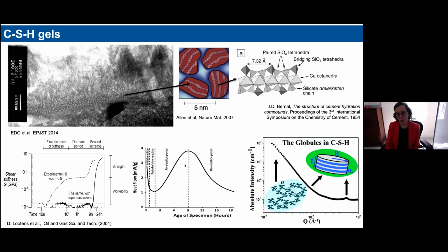Okay, so the formation of the gel is associated, of course, with the development of the mechanical strength. And these are measurements with ultrasound of the evolving modulus of the material, in which the gel is forming and progressively densifying and solidifying, because the nanoparticles that compose the gel keep precipitating in the porous solution as the grains continuously dissolve over time.